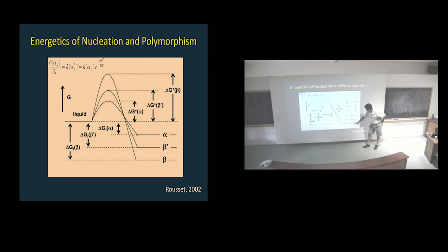I told you that the beta was more thermodynamically stable than the beta prime than the alpha. Hexagonal, orthorhombic, triclinic. And obviously in a free energy diagram like this, the beta would be at the lower energy level. But we must not forget the energy of activation. So the energy of activation of the beta form, even though you would say, oh, my driving force is thermodynamic, I'm going to go to the beta form, is the highest. Beta prime is the least, and alpha is the lowest.